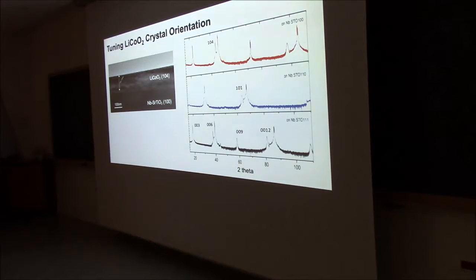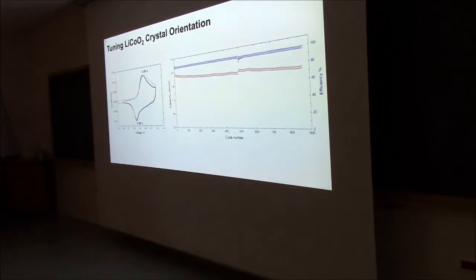And also there you can grow this nicely in oriented layers and study the performance there. And there we see that these two peaks are around 4 volt, and if you cycle them, this is also almost 900 times. You can see the capacity drops a little bit. This is where we did a different measurement, and then you go on.